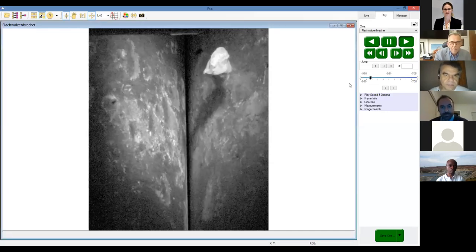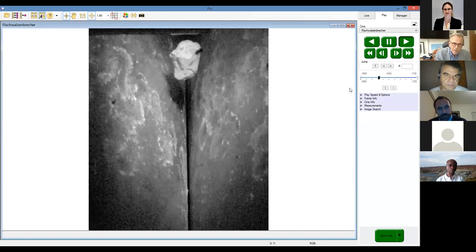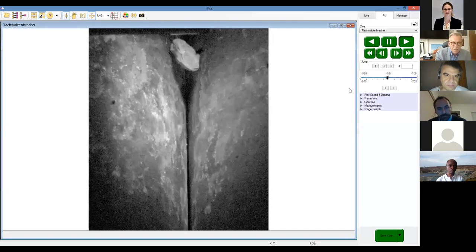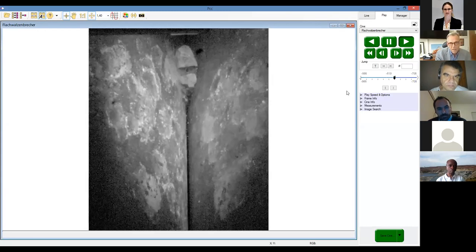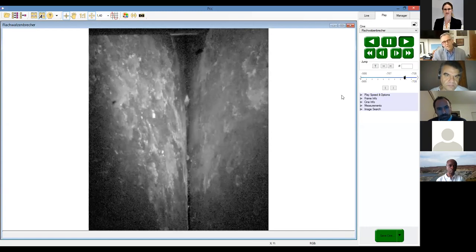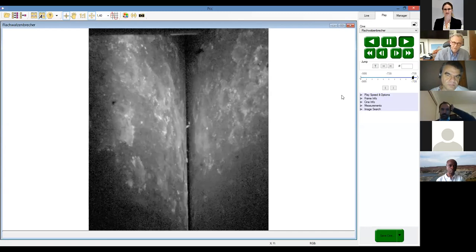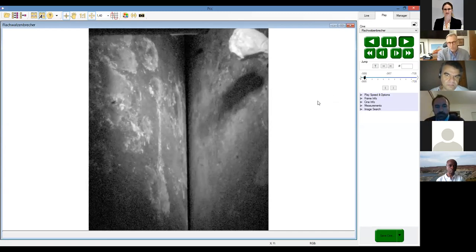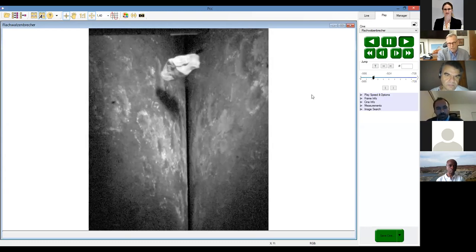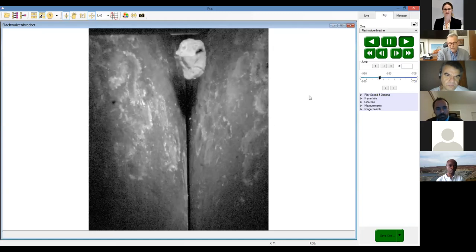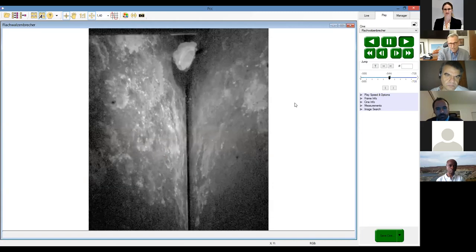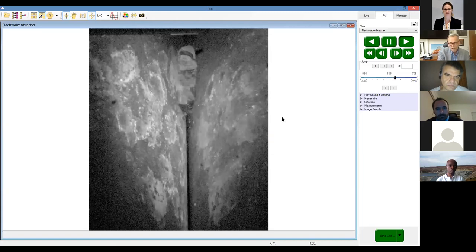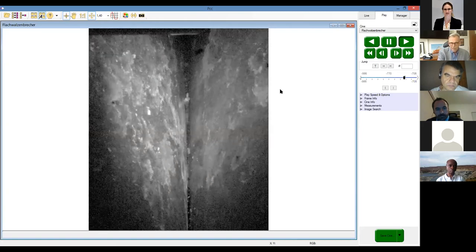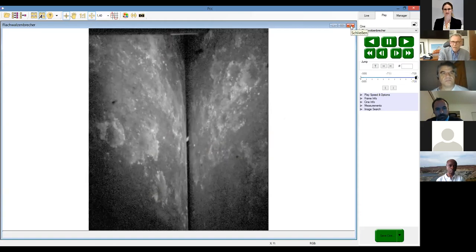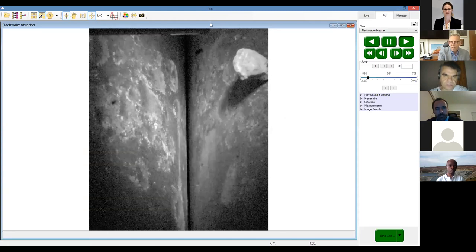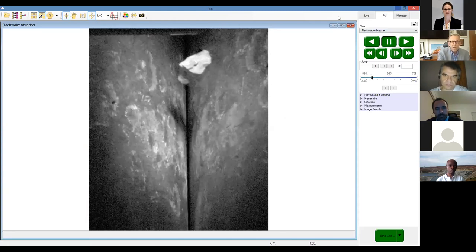So you see, we are talking about a flat-face double roll crusher. We have just single particle comminution here. As you can see, this particle has a diameter or a maximum length of about 16, 18 millimeters. So it has essentially a lot of space to escape there. You can see there are no other particles preventing it from moving. And still, with these single particles fed to this flat-face double roll crusher, of course with a very narrow gap, you see that at a certain point, the material has not enough time to escape anymore. And then in the center, you're producing these flakes and you're producing extremely high peak loads.